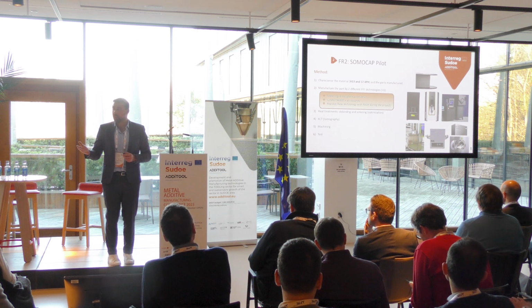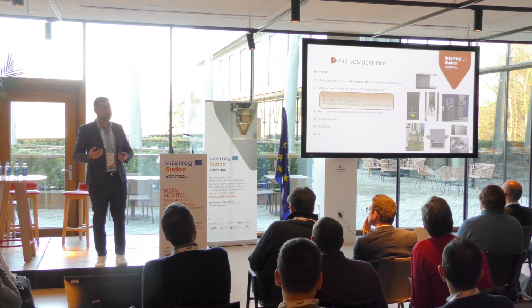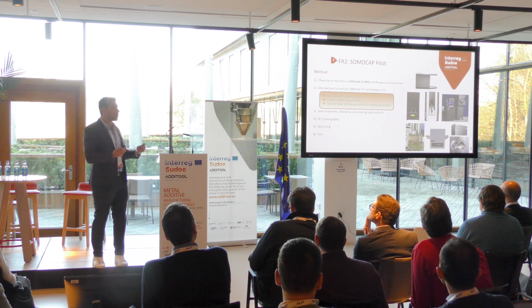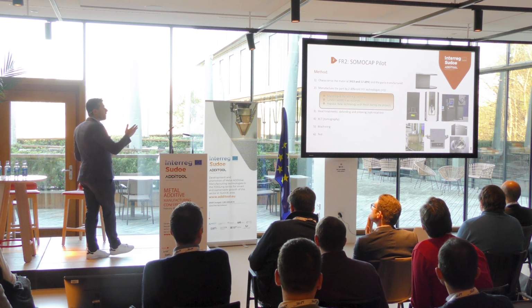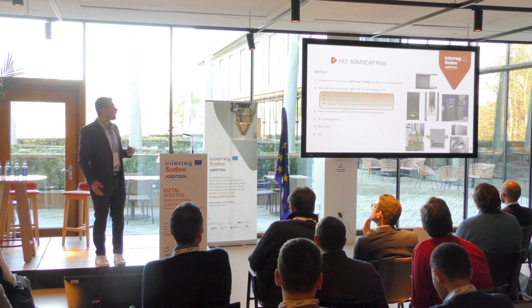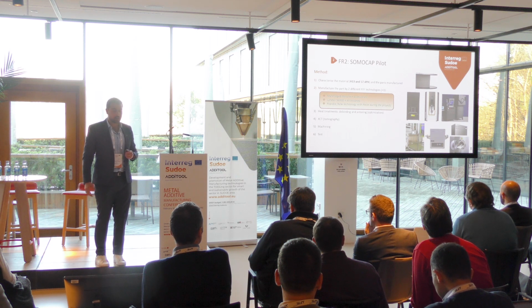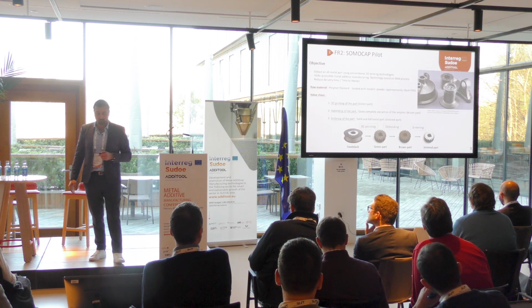We perform some tomography on the part to characterize the material, if there is some porosity, some cracking, bubbles, etc. We machine and test directly on the production lines of Somocap.